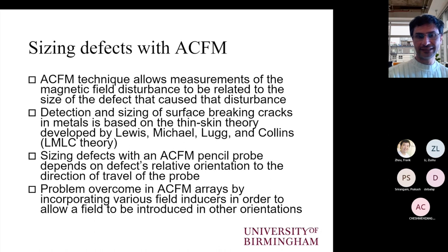In the case of sizing of defects, this is based on the theory developed by Lewis, Michael, Lugg, and Collins when they were at UCL. So the idea is to relate the length and the depth with the BZ and BX responses. In reality, however, the calculations have already been carried out during tests in the lab. So these signals have been calibrated, and also they have been related to calculations based on the mathematics that have been developed in the thin skin theory.